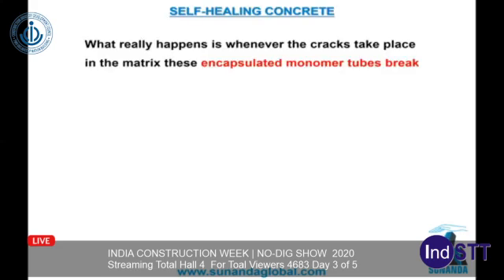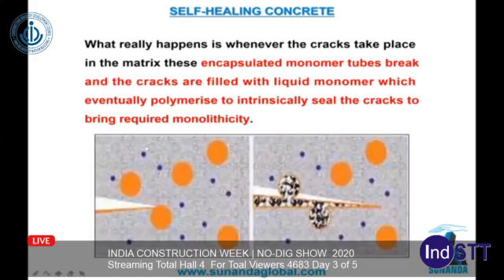Now, whenever a crack develops, like we are seeing in this picture, in the first picture the crack has started to develop, and in the second picture the crack has developed more. Whenever the crack appears, the nano-encapsulated monomer tubes will accumulate in this crack. The encapsulation will break, and then that monomer will convert into polymer, filling the entire empty space, resulting in no loss of structural strength, concrete strength, or ingress of moisture or chlorides from outside.